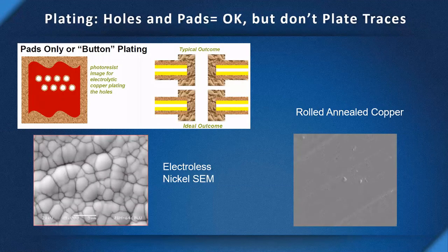One of the things I do want to talk about, for those not familiar with flex fab, is something called button plating. Very important in flex. The rolled annealed copper has a very good structure for bending, especially when the grain of the copper is oriented correctly. You don't want to put electrolytic copper on there, and in fact, it's even more important not to put things like electroless nickel there. Electroless nickel builds up in nucleation sites, and then you have these grain boundaries, and I have an image on the lower left. If you bend that structure, it'll crack and then transfer the crack into the copper trace underneath.